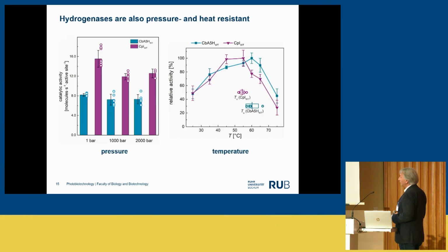for application. What is also very interesting, the enzyme is extremely stable, more or less more stable than any other protein. So some tests. We tested with pressure, and at 2000 bar, the enzyme still produces hydrogen. We look at temperature. We have a temperature optimum at around 60 to 70 degrees, so it's also quite nice.